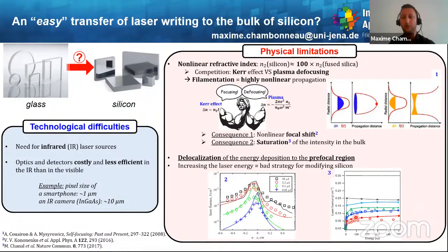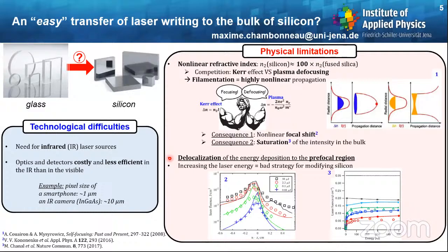So when you increase the energy, the laser fluence, so the real deposited energy inside silicon, is limited and saturated. And when you take those two consequences together, you can conclude that there is delocalization of the energy deposition to the prefocal region. A consequence of this is that increasing the laser energy will be a bad strategy for hoping to modify silicon.